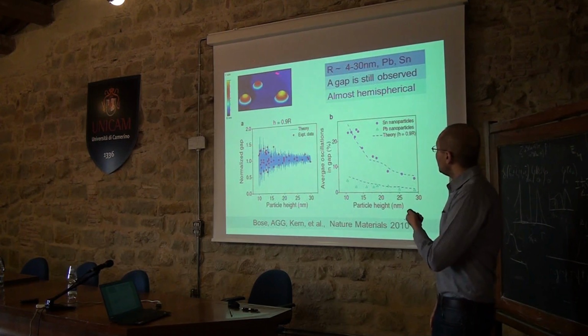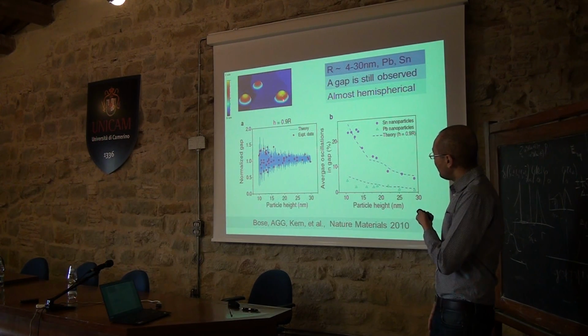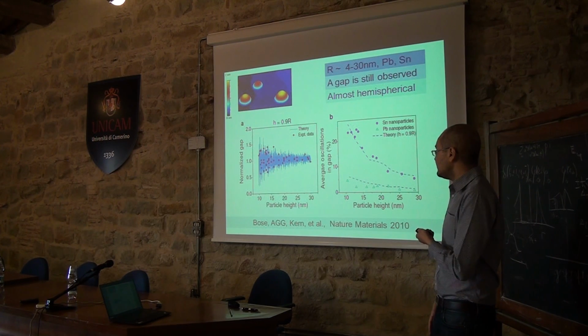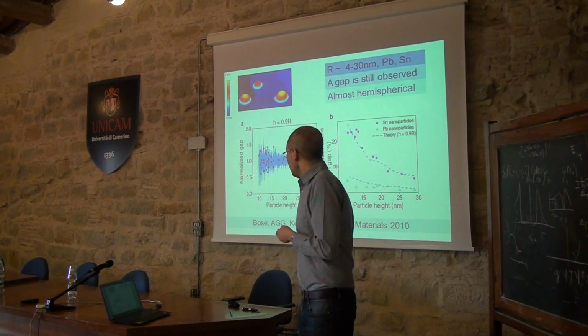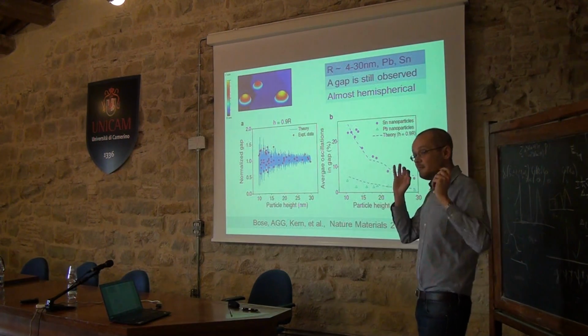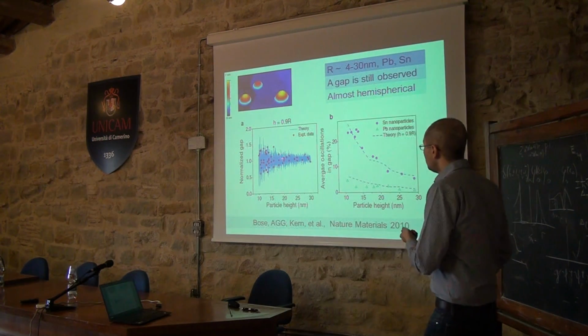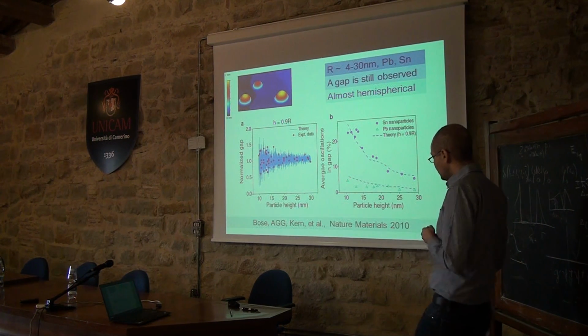Then a little bit later, the group of Klaus Kern and Gita Bose in Stuttgart managed, for the first time, to produce this type of single isolated grains of about 10 nanometers. And these are also the experimental results. They found that by changing the size of the grain a little bit, you see a huge fluctuation of the gap. And what was surprising is that just by using a plain, simple model of BCS with no free parameters, just plugging in numbers from textbooks, you could get a very good agreement between theory and experiment. I participated in this work, which was published in 2010.